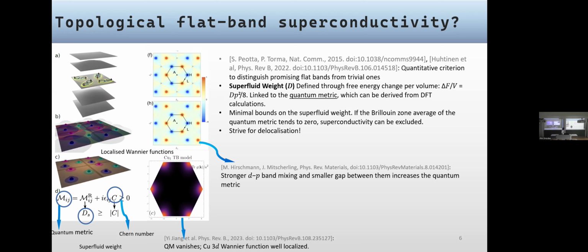And interestingly enough, the calculation of this parameter, which is called quantum metric and which is used to prove whether superconductivity can exist or not in the systems, was actually used by some studies in connection to the LK99 problem. And the researchers kind of disagreed on some parts, because one paper found it to be absolutely trivial, and the other, using different sets of parameters taken from different DFT calculations and building tight-binding models with different hopping parameters and so on, came to the conclusion that in some cases those bands might be non-trivial as well. And the value of this quantum metric increases with the stronger hybridization of the neighboring orbitals.